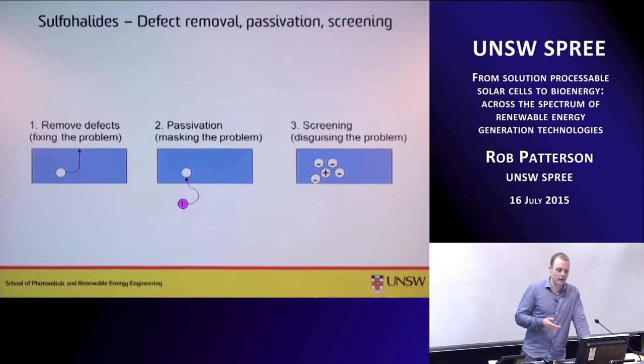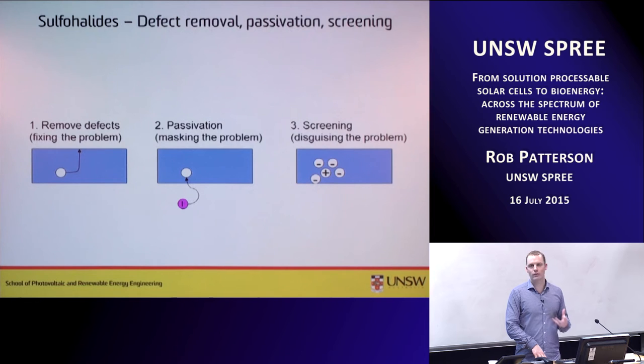After we try to remove any defects, maybe get any point defects to migrate to a surface, after that, passivation. Any defects which end up staying in the material, anything that we don't want in there anymore, we try to mask that. With our colloidal quantum dot solar cells, we mask that with halides on the surface. With silicon, we like to use hydrogen. And that's our secondary approach. After that, we really have to start relying on the material to do some of the work for us. And that certainly is easier if we have a material that has some way of shifting charge such that it can camouflage any further problems in the material.